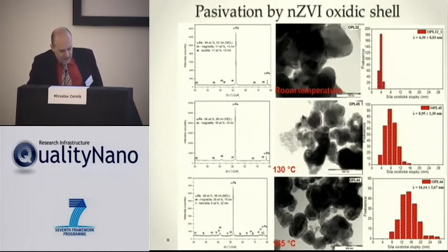The surface passivation by the oxidic shell can be done under different conditions, and I have here an example of 3 different conditions: oxidation at room temperature, 130 and 165 degrees, and you have the pictures of how the particles look. They are not different. On the left side, you have the X-ray spectra of the contents of iron and iron oxide, and you see that the peak of the iron is the highest in all cases, so most of the material is still zero-valent iron. And in the picture on the right, you have the thickness of the shell: if we increase the temperature, the thickness of the shell increases, so the protection of the particles is higher. We need to find the condition where the thickness of the shell is sufficient to protect the particles, but on the other hand does not decrease their reactivity.